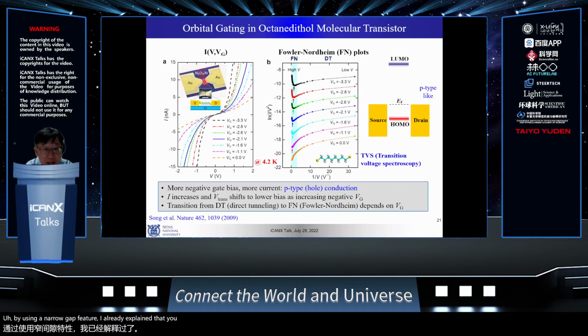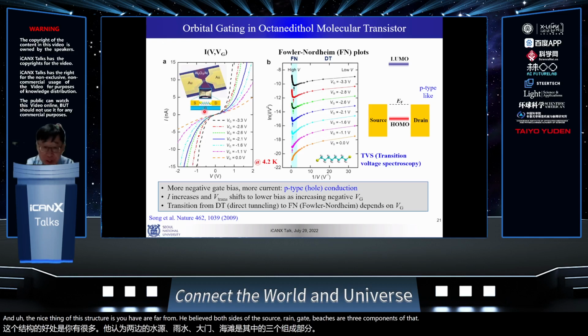And by using the nano gap feature, I already explained that you can create a nano gap here by electromigration Joule heating. And the nice thing of this structure is you have a bottom gate electrode. So it's a source, drain, gate, which are the 3 components of the field effect transistor. So by fabricating this structure, this single molecule junction, and measuring at 4 Kelvin, then you can get the transistor action by orbital. You can see this.